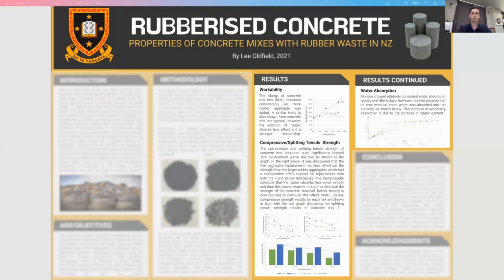The destructive tests, which are the compressive and splitting tensile strength tests, were impacted quite significantly from the addition of waste rubber. It was discovered that the fine aggregate replacement had less effect on the strength than the larger rubber aggregates, although beyond 10% replacement, we can see quite a decrease in compressive strength by approximately 60% in each mix.